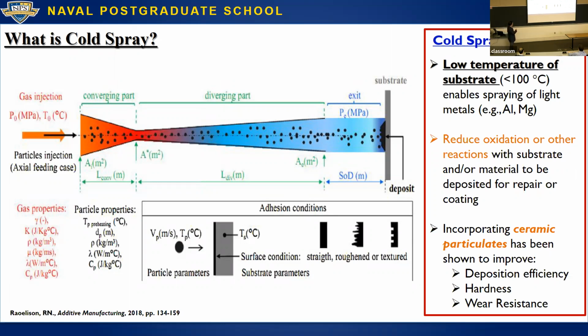This technique is called cold spray because it's cold relative to other thermal spray techniques like plasma spray or HVOF, and cold relative to most traditional metallurgical processing. In this case, we're not trying to melt the metals. It's a solid state processing route, which in itself is quite interesting. What you do is you take it through a heated gas. The newer systems are going all the way to 900 C. Traditionally, most cold spray was done for aluminum, and for those systems, you really just have to go to 400 C gas temperature.